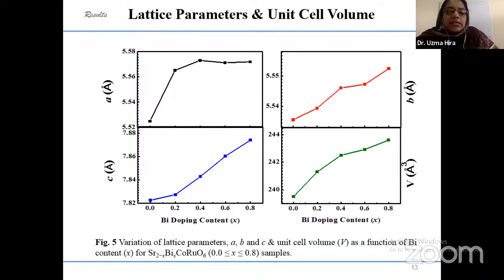And you can see that all the lattice parameters A, B, C, and unit cell volume V are increasing with increasing doping content. As you know, we are doping bismuth at the site of strontium, and the ionic radius of bismuth is smaller than strontium. So technically, our unit cell should shrink, although it is expanding. So what could be the possible reason why our unit cell is expanding?